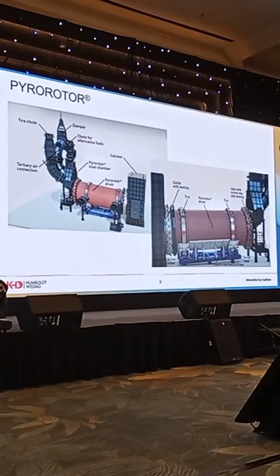So here is an overview of how such a pyrorotor looks. From my point of view, I would say it looks like a ball mill connected to the calciner. At the end, it's like a small kiln, like a small rotary kiln. So you see here the drum of the pyrorotor itself, the tires, where it looks more like a small kiln. You see the connection to the calciner itself, and also here the connection of the tertiary air, which is used as burning air for the pyrorotor, the feeding chute for the alternative fuels, and also, if you want to use complete tires, the separate tire chute for giving the tires inside this pyrorotor.